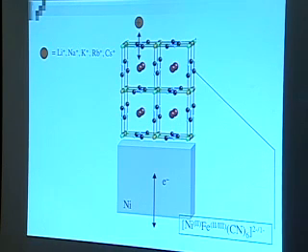Okay. How do we make this? We simply take ferricyanide, dump it into solution, take our electrode and set it at a positive potential, generate nickel ions by anodizing the electrode. The nickel ions shoot out into aqueous solution. You make nickel ferricyanide, and either you would make so much nickel ferricyanide that you consume your electrode and you would not have a future career as an assistant professor, or you could be fortunate like Professor Bocarsly and you would find out that it's a self-limiting process.